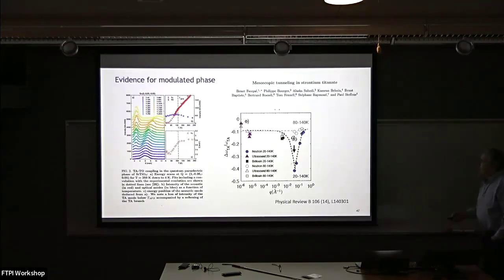Right, so then if you look at that, what you can really do is pick a couple of temperatures, which they did here, and also a bunch of different Q vectors, and look at the change in the acoustic phonon frequency from one temperature to another. Now, because everything is pretty ratty down at low temperatures, they're showing only down to 20 Kelvin. So what you see is that for a Q vector somewhere around 0.02, there's a softening by about 50%, which is actually quite a lot.